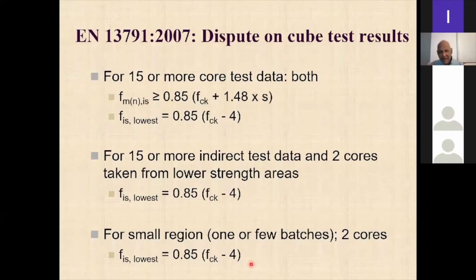So if there's a batch with a low cube strength, you should not worry only about that batch, because the overall concrete supply will be satisfactory. So that is why this target is not very difficult to achieve, right? So if you have a grade 30 concrete, the 30 minus 4 is 26, 0.85 of that is only something like 23 or 22, right?